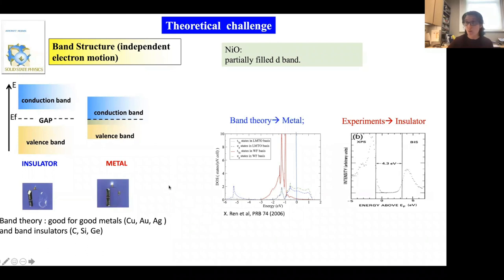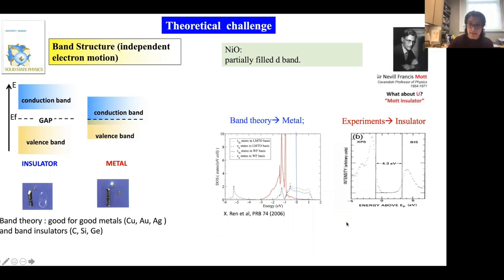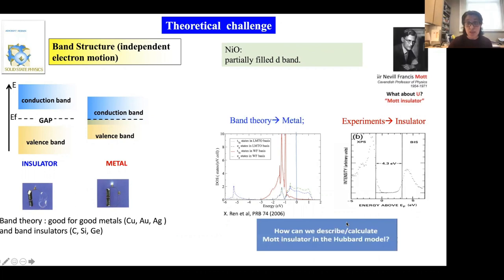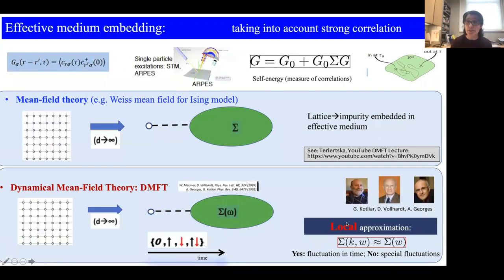This theory is built on the independent electron approximation, so it's really good for some simple metals and some band insulators. But when applying this to some prototypical example of a correlated Mott insulator like nickel oxide, we see that the density of states at the Fermi level doesn't exhibit the gap, which is experimentally seen. Okay. And the reason it doesn't capture this transition is due to the improper treatment of strong correlation effects. Okay, so how can we incorporate strong correlation effects into the analysis and capture the Mott metal insulator transition?